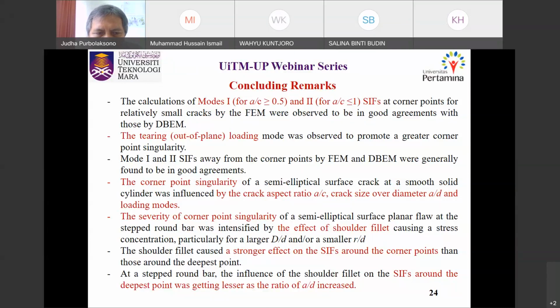And then we can also notice, for example, the effect of the crack aspect ratio, crack size or diameter, and also loading mode will influence the SIF. As for the step bar, the severity at the corner point is intensifying the effect of the shoulder fillet, probably resulting in stress concentration, especially when D over d is large or R over D is small. So here we have the severity of the corner point singularity.